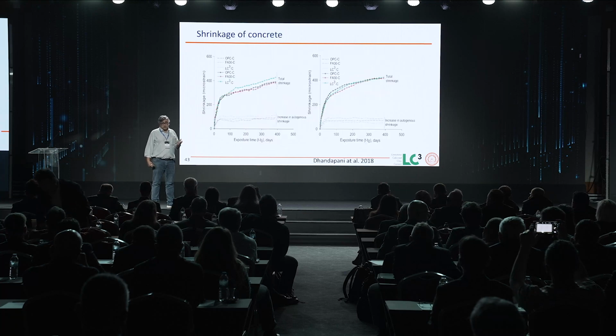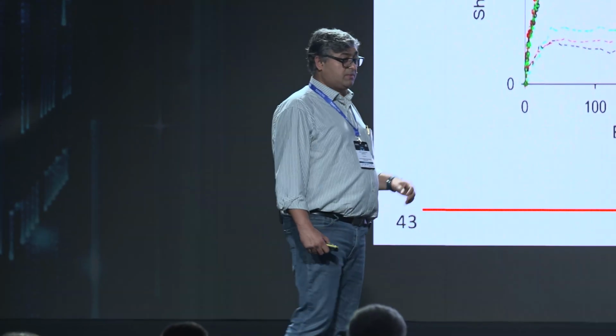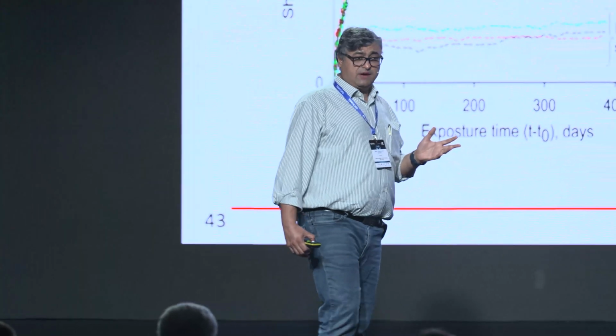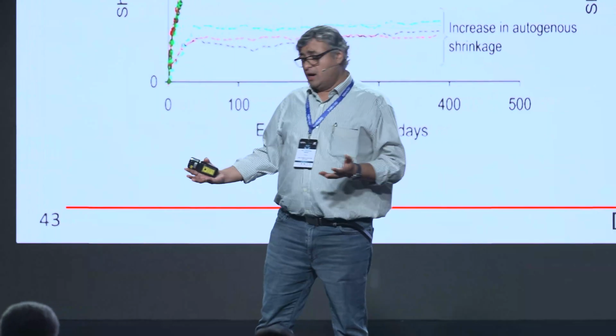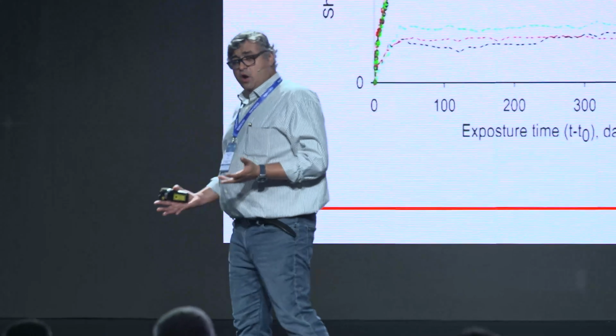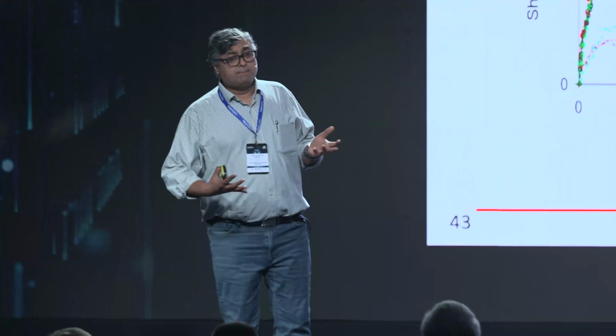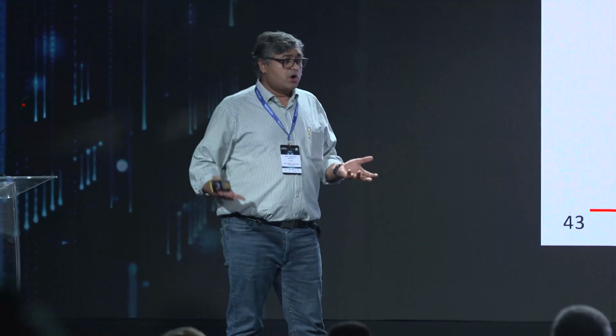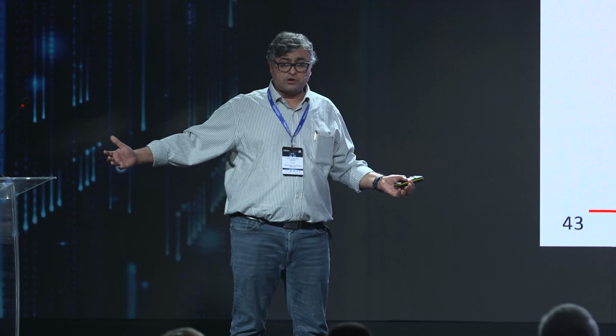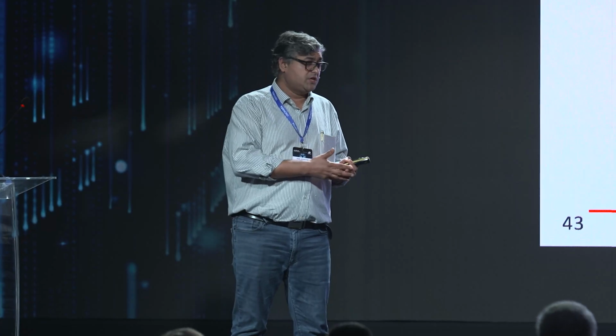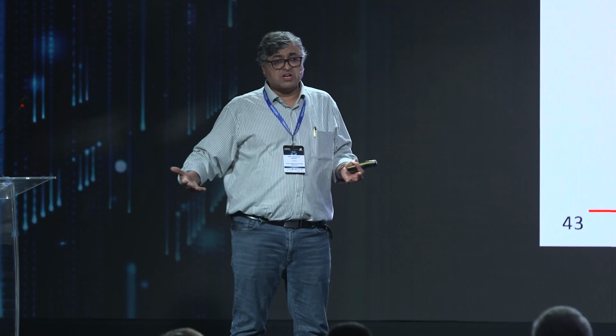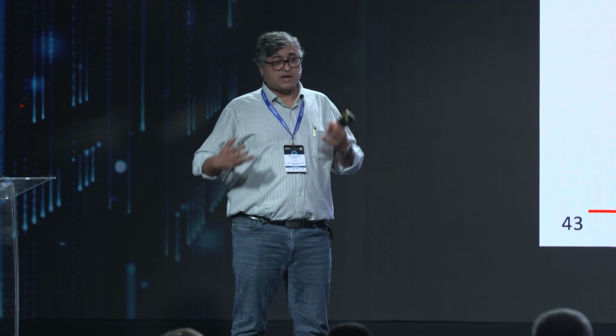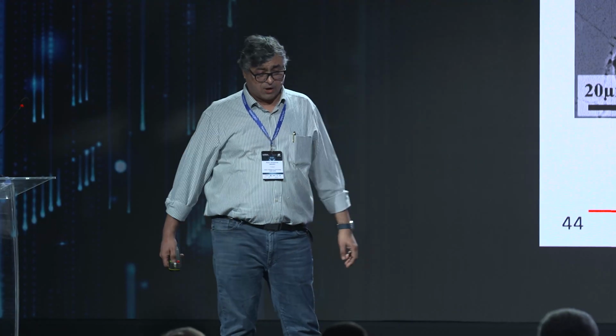Creep seems to be lower from the literature, shrinkage seems to be similar. Creep is a question that we have to answer because you require a lot of facilities to be able to measure creep. But then, like I said, the most important application for creep is pre-stressed concrete. From the measurements that we are doing on the pre-stressed concrete, we do not see much of a difference from OPC and LC3. So we are very confident about those things.